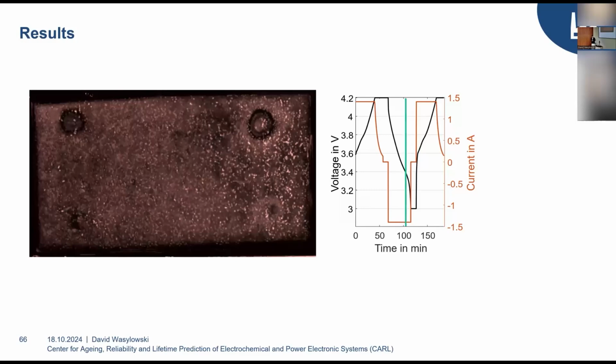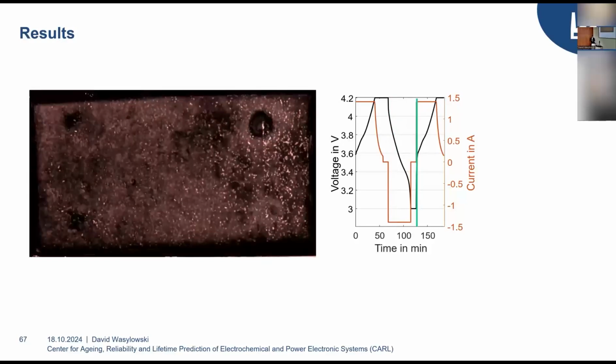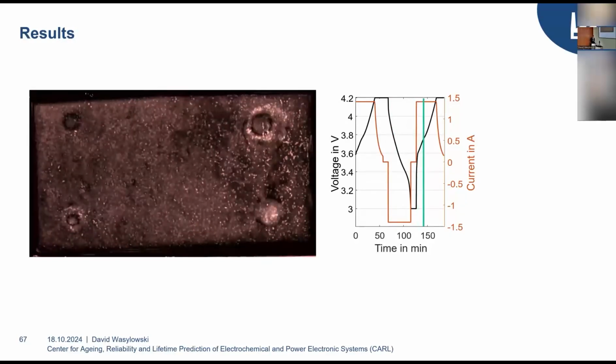We can recover a small portion of it, and this is what we are seeing here. We call this effect also lithium stripping. So we are actually using some of the lithium that was deposited for further cycling. And within the next charging step, we see those indications growing again, confirming that this is actually a reproducible effect here.